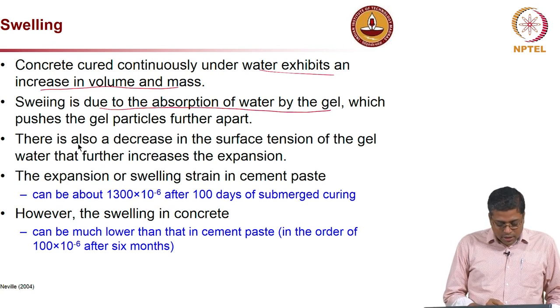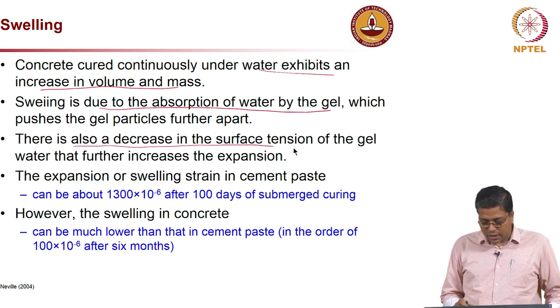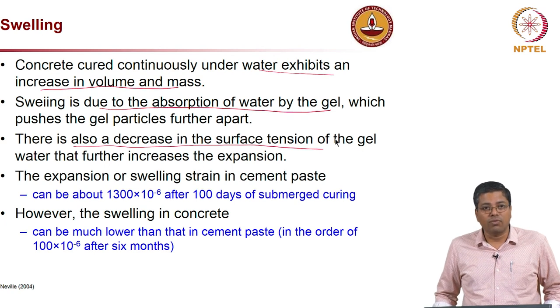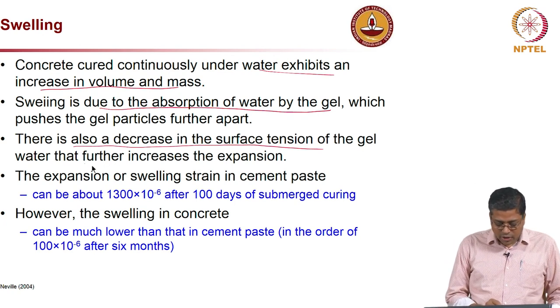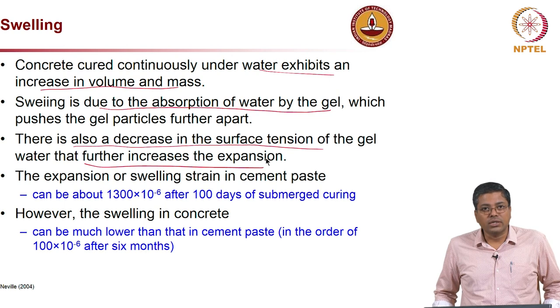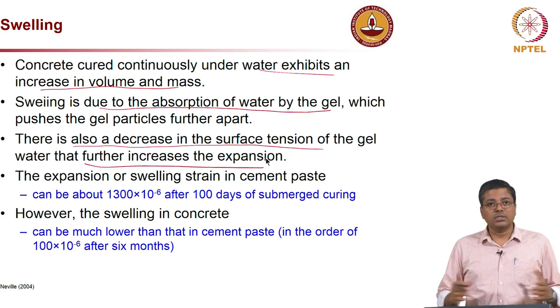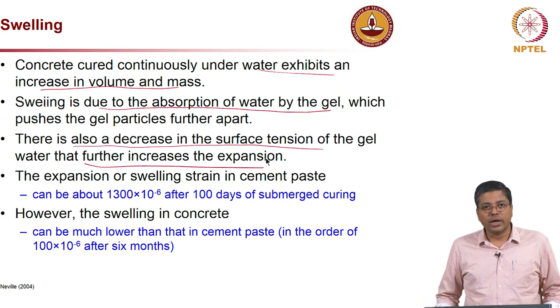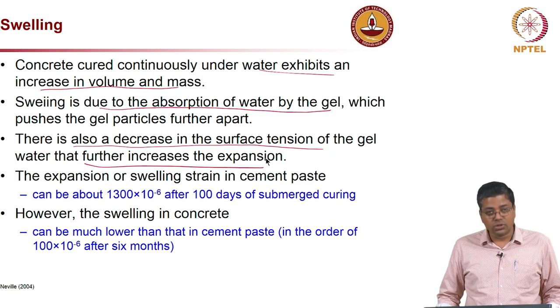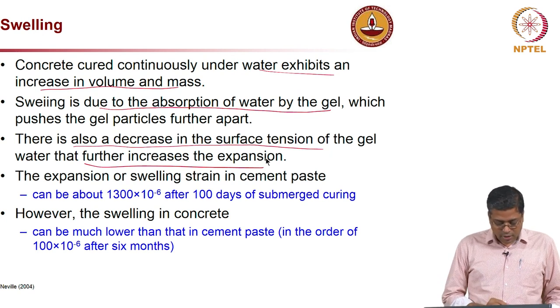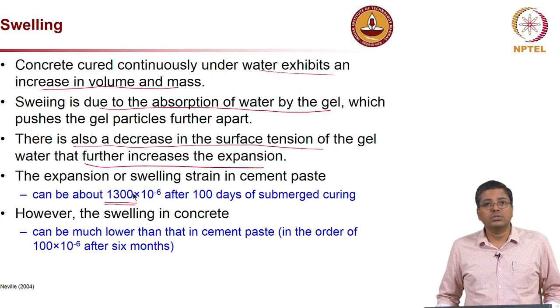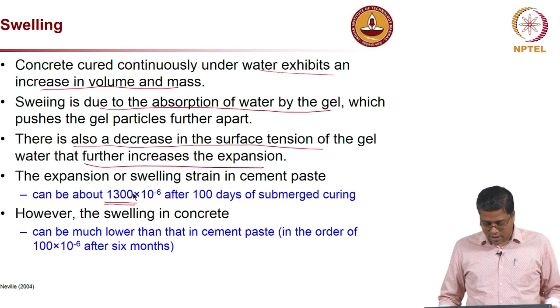And another mechanism is a decrease in the surface tension of the gel water that further increases the expansion. So, surface tension decreases, which leads to expansion, eventually leading to expansion of the concrete. Now, what it could be is in this range, about 1300 microstrain after 100 days of being submerged.